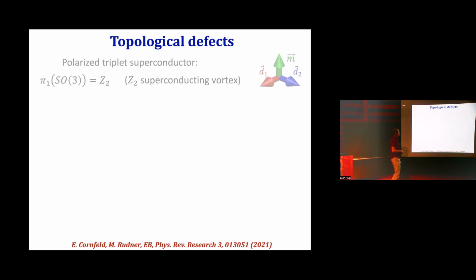And it turns out that in a fully spin polarized triplet superconductor, where the order parameter space is SO(3), these are different. The topological defect is characterized by a Z2 index. So there are no vortices and anti-vortices, there are only vortices. Two vortices can always destroy each other, always annihilate each other. This is related to the mathematical fact that the homotopy group pi1 of SO(3) is equal to Z2.